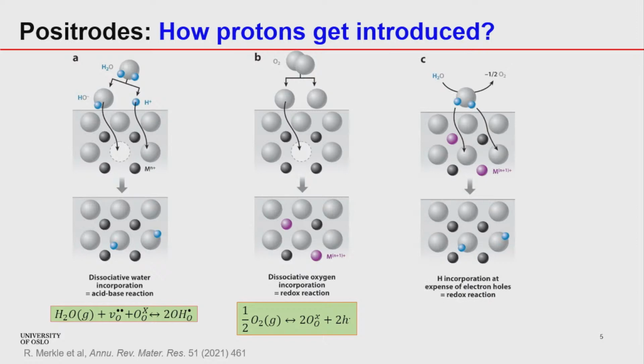The next reaction is a type C reaction, which you can say is a combination of A and B reactions together, called the hydrogenation reaction, where a proton is incorporated in the material at the expense of electron holes. So water comes from the atmosphere, oxygen leaves, and the protons go and attach to two oxide ions. And when oxygen is leaving, it gives electrons to the already existing holes, and hence we eat up the holes. So here we can introduce protons even if we don't have oxide vacancies. This is called the hydrogenation reaction, and it is important to remember because we will see examples in some next slides where even though some of the materials did not have oxide vacancies, they still showed better performances in electrochemical studies.